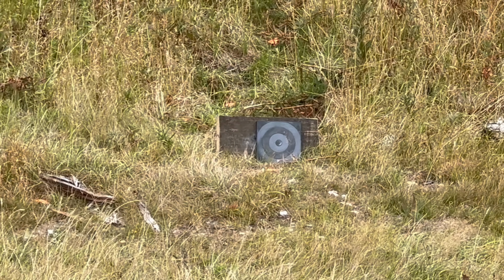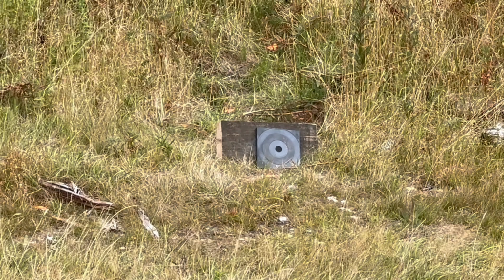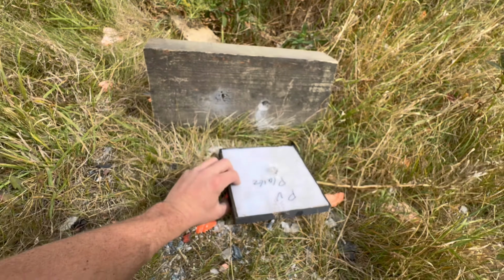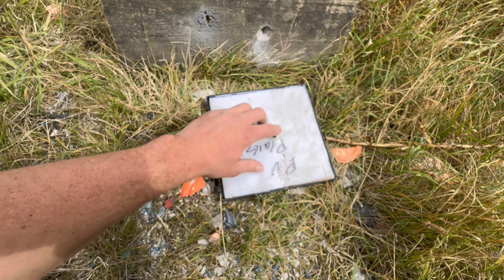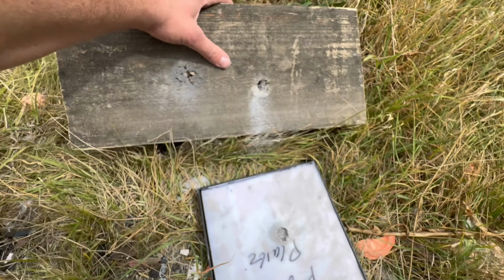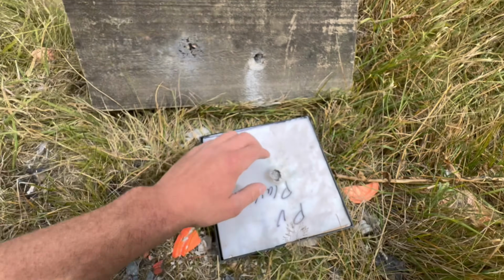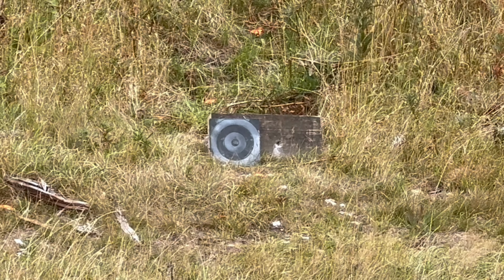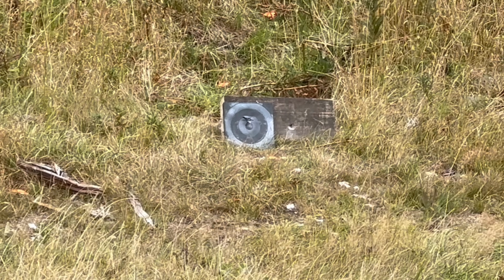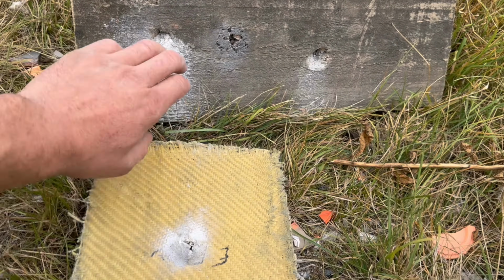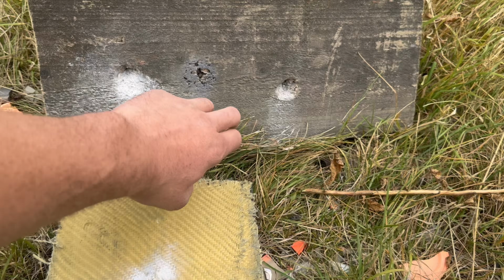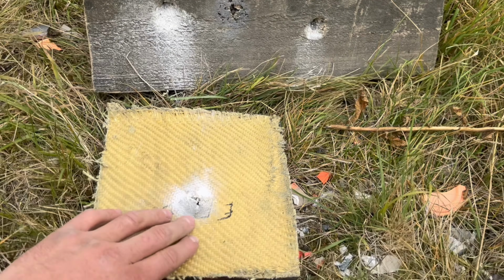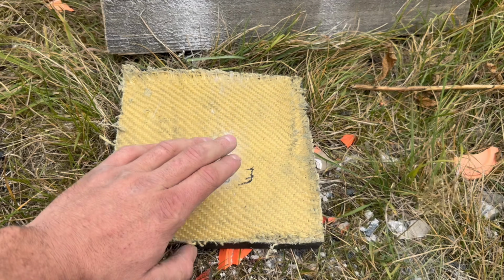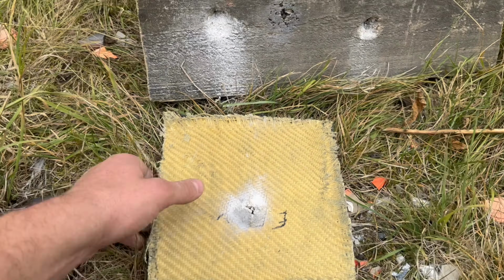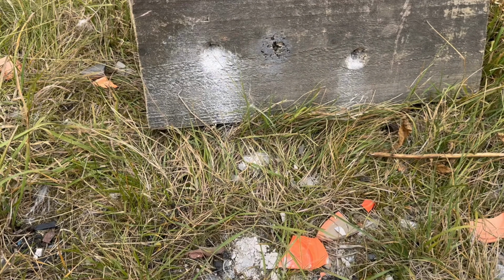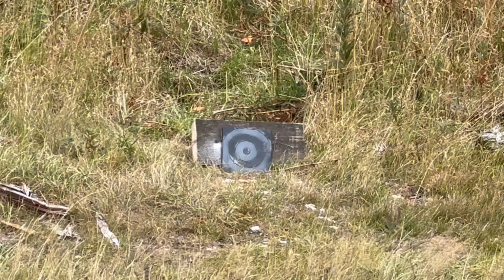Back to it with the 2 layers with the plastic backing. This did go through, although you can see that the ceramic is working and slowing it down. It's just the plastic really didn't do much at all. And then with the Kevlar backing with the epoxy, this did go through, although the divot on the wood did seem to be shallower than it did on the plastic, so maybe the Kevlar's a little bit better. You can tell by the size of the divot that it is actually slowing the round down as it goes through. So I think the ceramic's now doing its job, it's just the backing plate isn't.